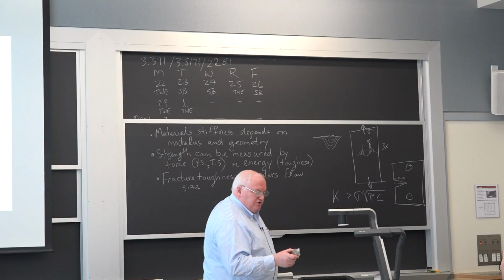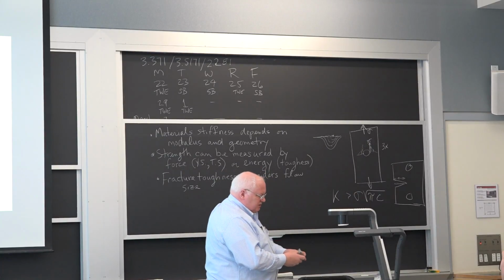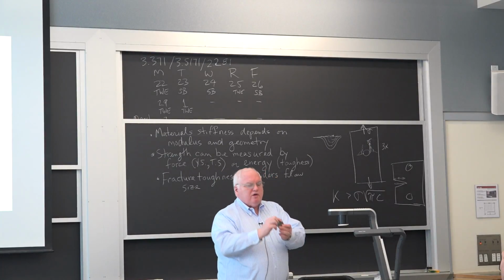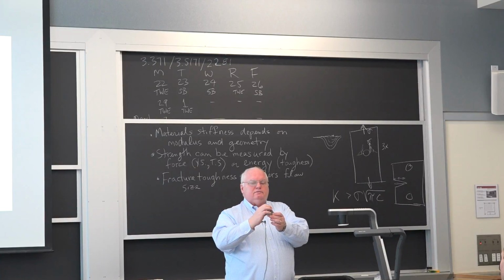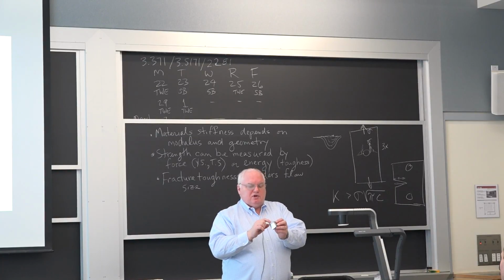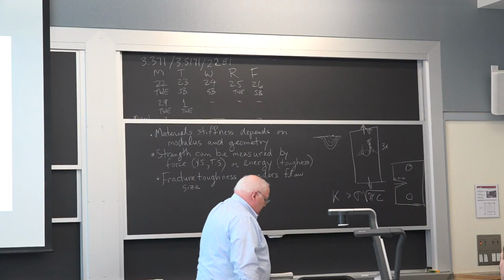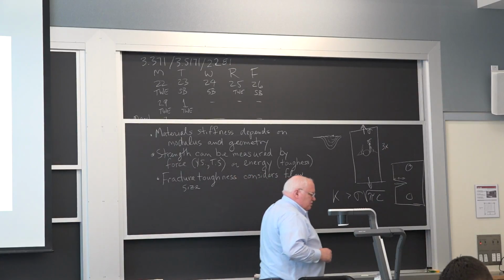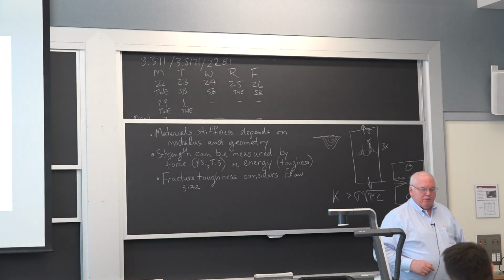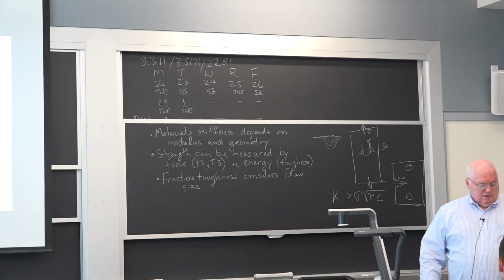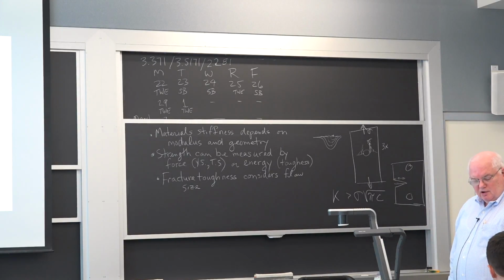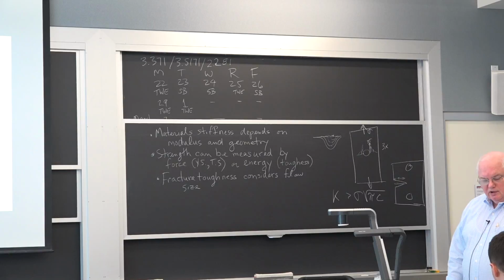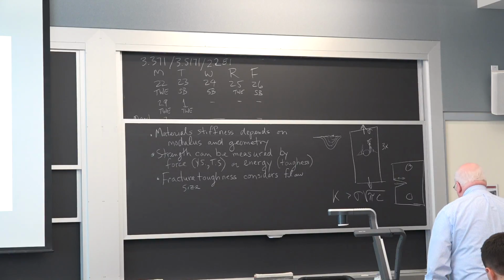This is a piece of the fracture surface. If you look on the edge of this thing, as I pass it around, you'll see a little bit of ductility. It started to stretch, but then you see the rest of this is just a terrible brittle fracture because they didn't heat treat the steel properly. And they had one of them let go in France, almost killed somebody, but didn't. And then they killed someone in China.